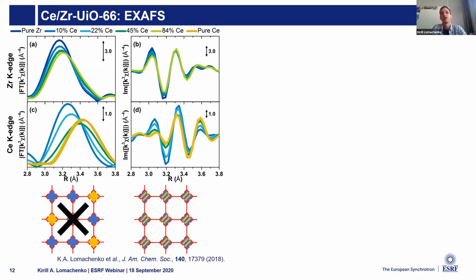Instead, it's clear that we have a mixture of cerium and zirconium in the cornerstones. Again, qualitatively looking at the data, at zirconium K-edge we have a very high intensity for low loadings, and the intensity does not change quite a lot for materials with a loading above 20%.